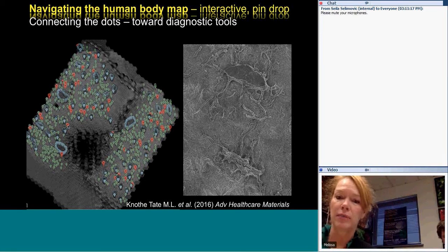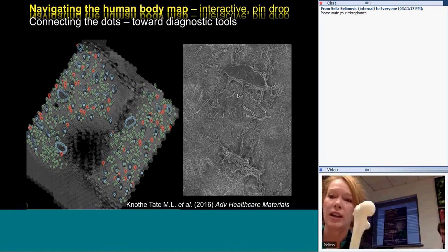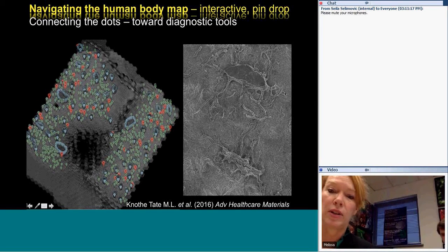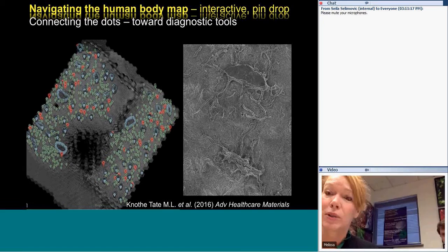And the other interesting thing, I think, is the etching protocols. I don't think we talked about them very much, but we get this perfectly planar surface, and then we can use atomic force microscopy protocols we developed way back in the days when I was a grad student in Zurich, where we specifically etch away the mineral or the organic component, so we can really start to pick up the different components of this large structure and this sort of resolution. And you can't see it here, but in the best resolution of this device, we can see down to individual collagen molecules, collagen fibrils. It's really mind-boggling.